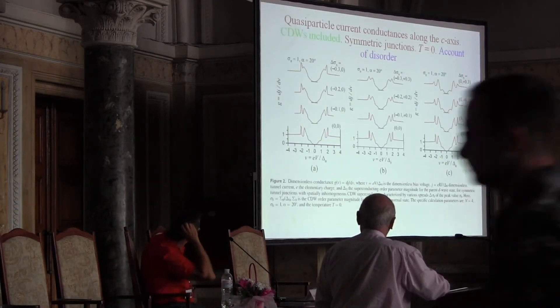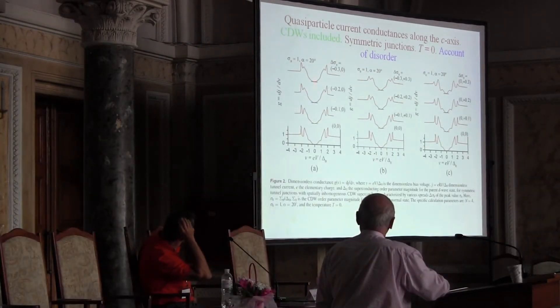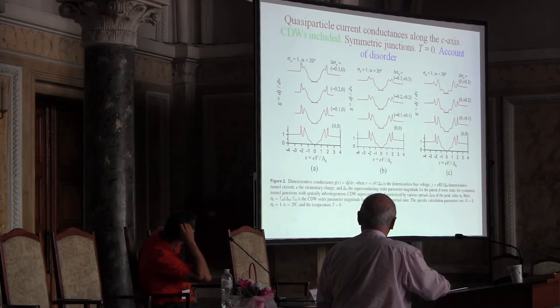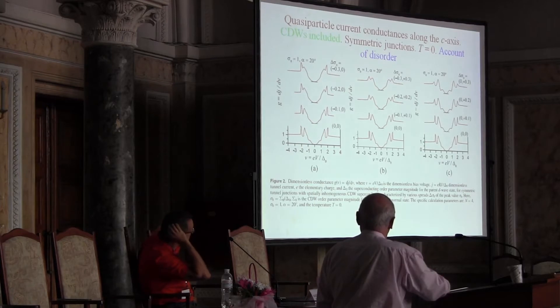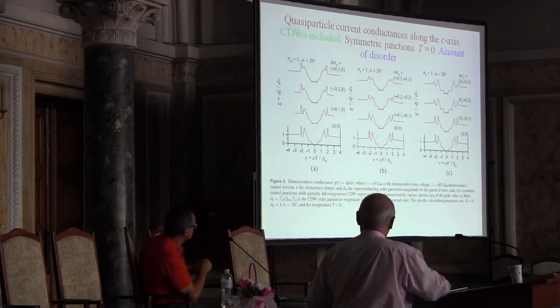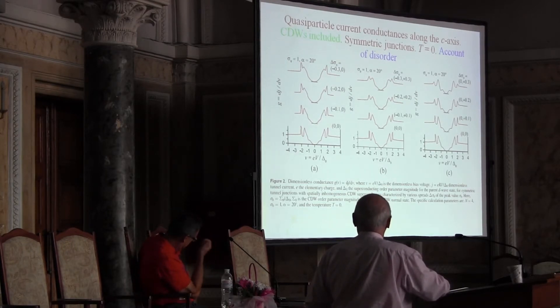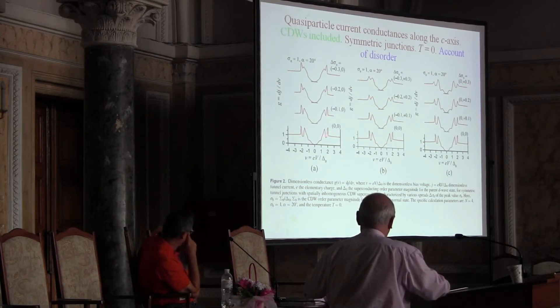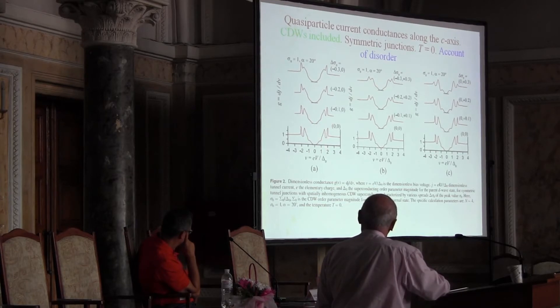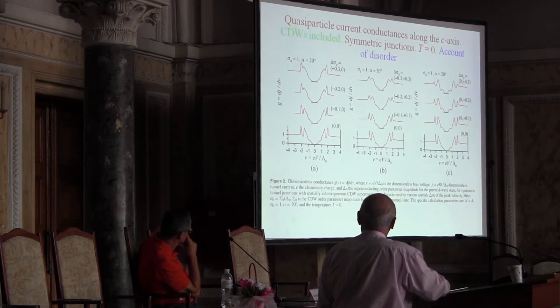When we have this disorder, we calculate it with several properties of disorder, and when the parameter responsible for the charge density wave changes, when it is, we have a wide distribution. When we take into account this distribution, instead of this behavior, we have some smeared behavior, which is really observed in the experiment.